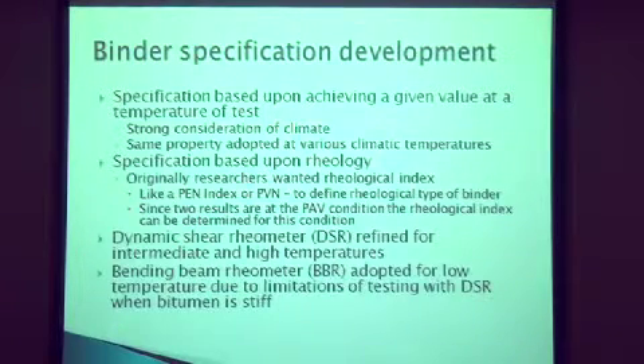So, in terms of this specification, what was different with the SuperPave specification versus the earlier specifications? First of all, in SuperPave, we have a very strong consideration of climate. The biggest difference with the SuperPave specifications is we have the same property adopted, but we test that property at different temperatures. If you go back to the pen specification, we have maybe 50 pen, 70 pen, 100 pen, but we do the tests all at 25 degrees C.